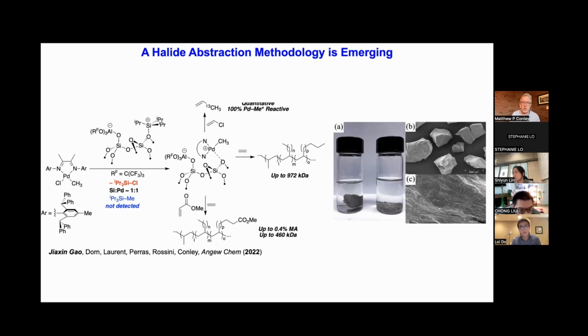There's this relationship on silica-supported catalysts where you always kind of have this 70-30 mixture. So 70% where the silica surface is acting like a pure X-type ligand, and 30% where it's behaving as an LX-type ligand. In this particular system, silica is purely an L-type ligand, but it's still an amorphous support, different chemical environments that we really don't know how to probe.